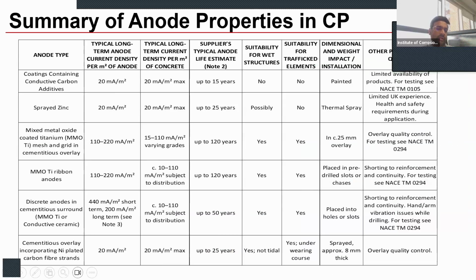So in summary, we have these kinds of anodes. Conductive coating anodes, typical current density required is about 20 milliampere per meter square, can extend the life to 15 years. However, cannot be used for wet structures or traffic elements.